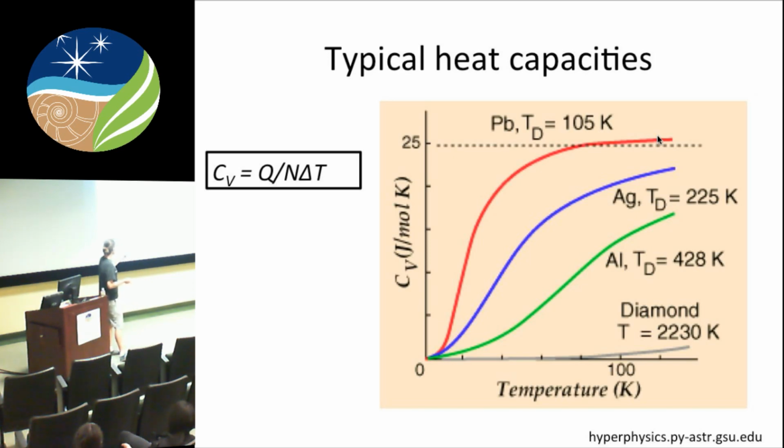But the heat capacity itself is actually changing as a function of temperature, and that's because at low temperature, there are vibrational modes that aren't excited, whereas at high temperature, all the vibrational modes are excited. And with increasing bond strength, going to very strong, very tightly bound materials like the carbon atoms in diamond, the heat capacity gets much smaller at fixed temperature because more and more temperature is required to liberate these degrees of freedom, at which point they contribute to the heat capacity. With pressure, how would this change? Well, if everything was so simple, like in this picture, all these curves would just shift to the right because bonds get tighter, so more temperature is required to access those same degrees of freedom. But not everything's so simple.